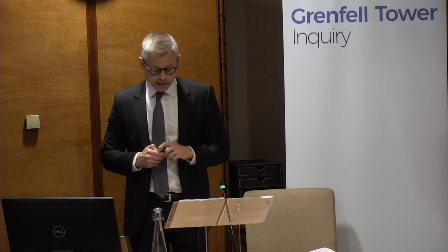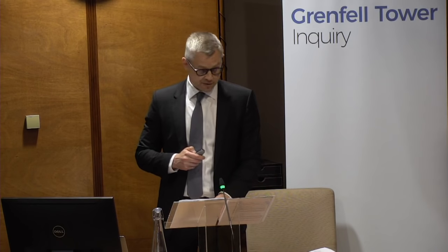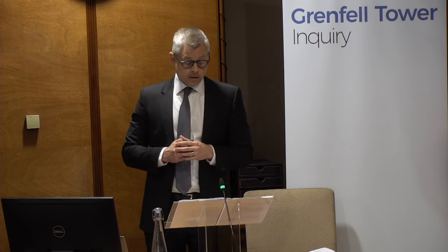And it represents, if you like, the ease with which the surface temperature of a material will change when exposed to heating. Materials with a high thermal inertia, such as metals, for example, are comparatively slow to heat at the surface, all other factors being equal. Conversely, the surface temperature of a material with low thermal inertia, such as polymer foam insulation, for instance, will increase rapidly when heated. As I've already stated, pyrolysis is a temperature-dependent process. Thus, there is a strong coupling between heating of the solid and pyrolysis. Consequently, materials with a low thermal inertia, where the surface will heat more rapidly, will initially experience more rapid pyrolysis than materials with higher thermal inertia.